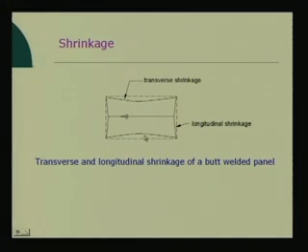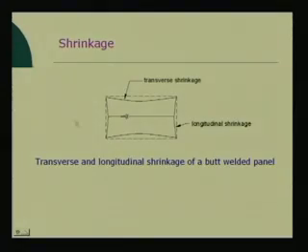deformation in the transverse direction is much more because the heat flow in a direction perpendicular to the welding direction is more, right? So that is what is shrinkage. So shrinkage can be of two types, transverse shrinkage and longitudinal shrinkage. Obviously, transverse shrinkage is more compared to longitudinal shrinkage.